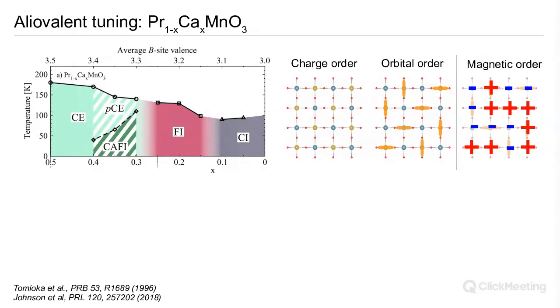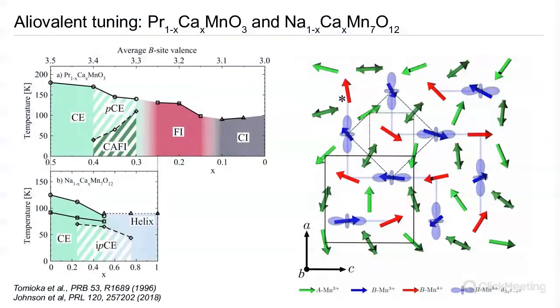We can actually create similar effects in the quadruple perovskites as well. So here, for example, we have sodium and calcium at the A site. This solid solution spans the same range of B site oxidation states. And we see actually the same CE phase is stabilized, but remarkably in this system, because we have additional manganese at the A site in the quadruple perovskite, we find these very complicated incommensurate type structures that can appear for certain compositional ratios of sodium and calcium.